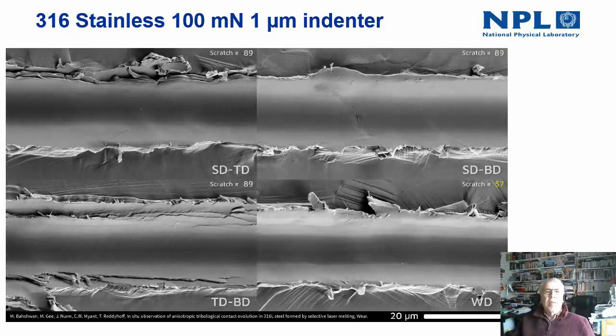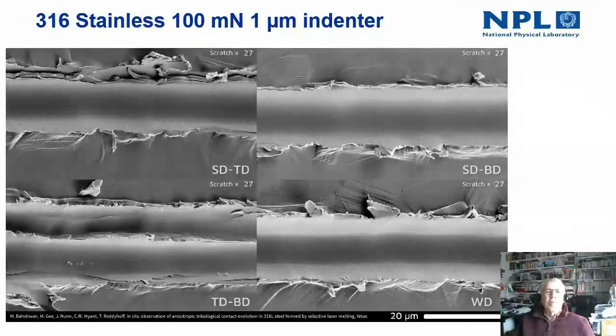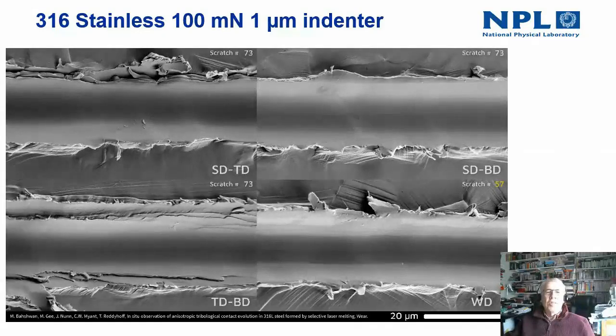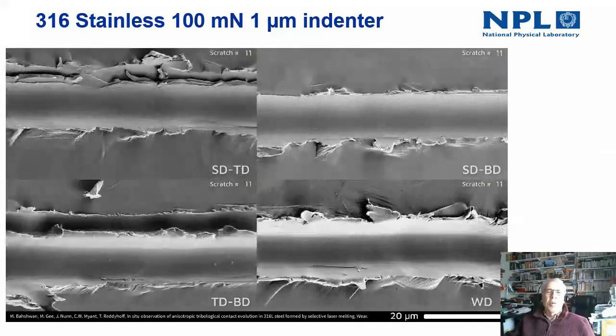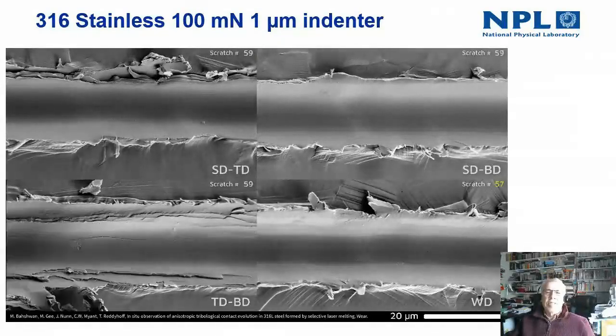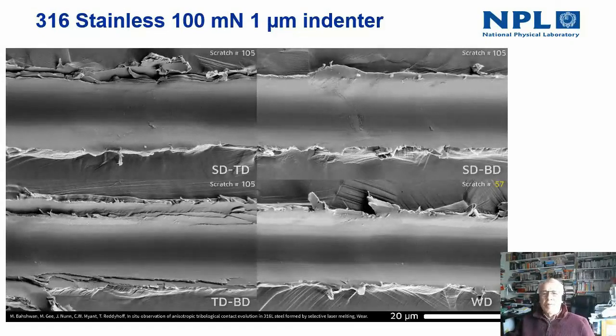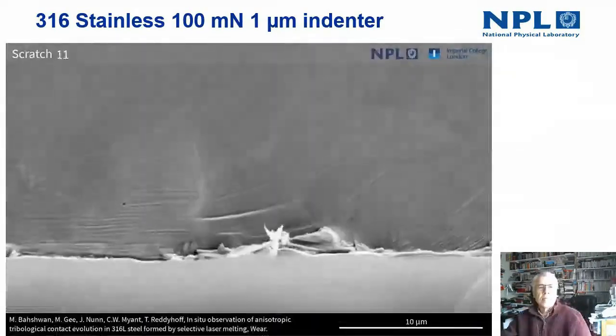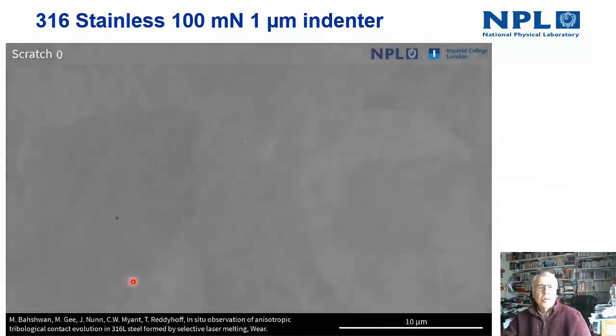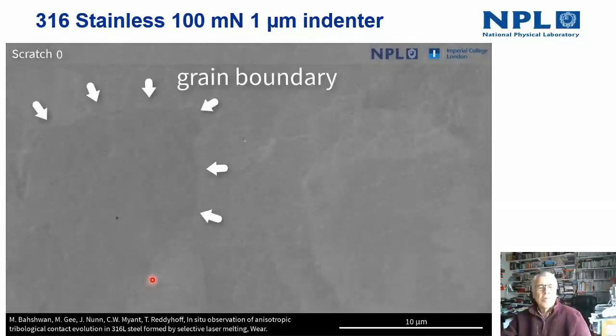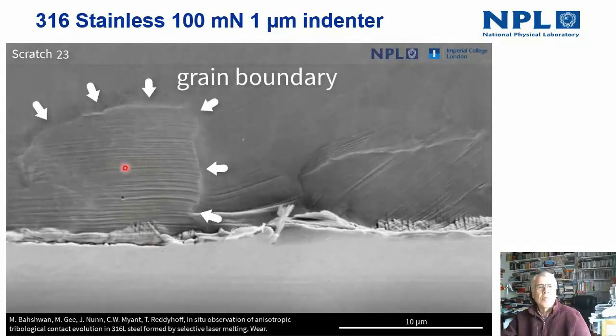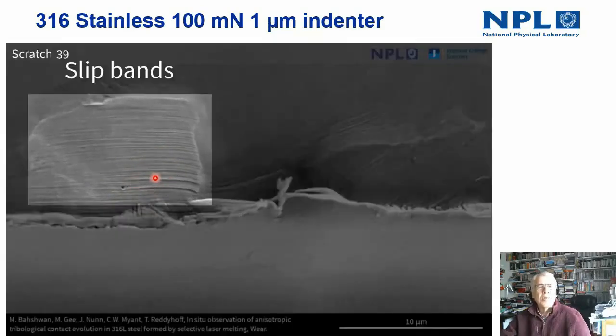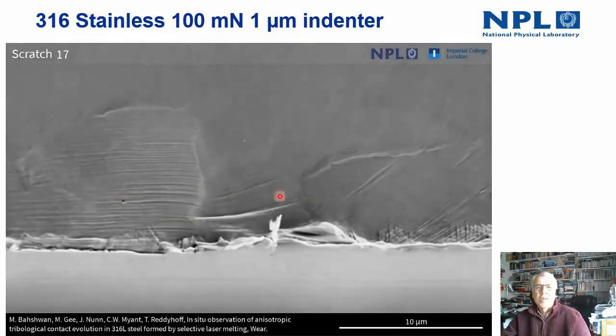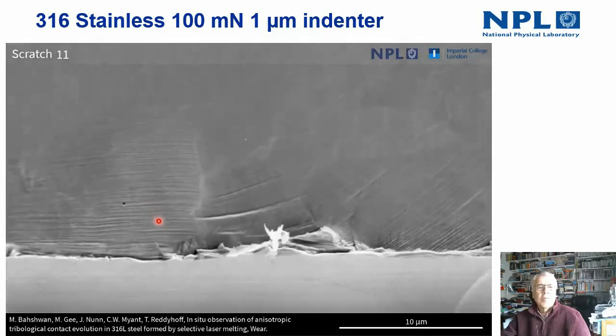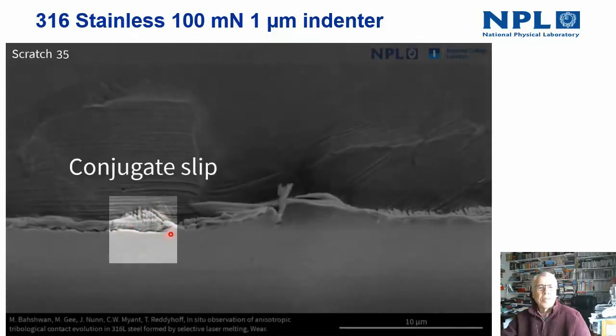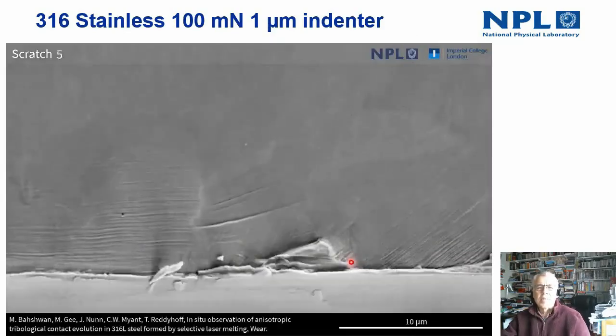And here they're looking at details of the differences in deformation that were found between one of the processing directions and another processing direction, and indeed comparing that to the original wrought material. This image shows the edge of one of the scratches, and it shows a lot of the detail to the side. So you can see a lot of slip line traces showing the detail of deformation in grains to the side of the material, and you can see something called conjugate slip, which is multiple slip planes being activated.